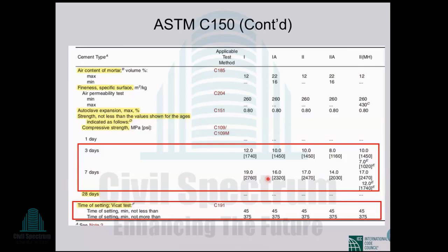In EN, there are two varieties of CEM1, 42.5 class and 52.5 class. So the 28-day strength of CEM1 must be greater than 52.5 MPa. But in ASTM, 28-day strength is not specified. In ASTM, 3-day and 7-day strengths are specified. For type 1, 3-day strength must be more than 12 MPa, and 7-day strength must be greater than 19 MPa. So this is interesting.